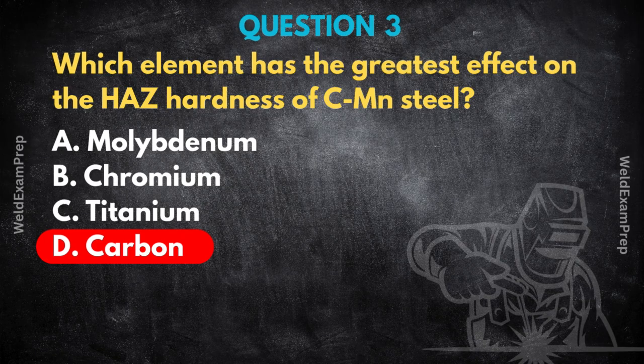And this dramatically increases the hardness of the HAZ, which in turn makes that zone highly susceptible to cracking, specifically the dreaded hydrogen cracking. Ah, hydrogen cracking again. Yes. Now, the other elements listed, molybdenum, chromium, they are important. They affect hardenability too, meaning how easily martensite forms deeper into the material. But in typical CMN steels, their direct impact on the peak hardness right there in the HAZ is much less dominant compared to carbon's influence on forming that hard martensite layer right near the weld.